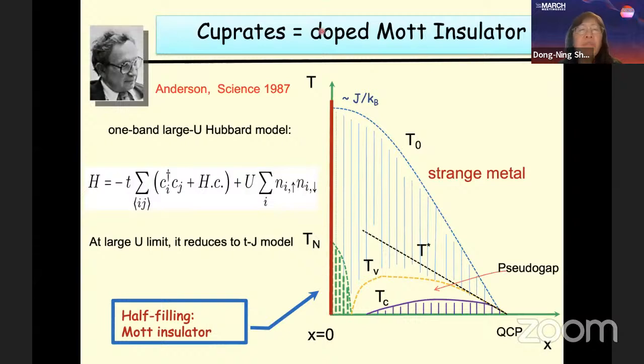So if we start from the doped Mott insulator, the simplest model is the one-band Hubbard model, with a hopping parameter for electrons and an on-site Hubbard interaction. On the square lattice, in the undoped case we have antiferromagnetic order. For the doped case, theoretical pictures based on the slave particle approach also give a possible range of superconductivity.